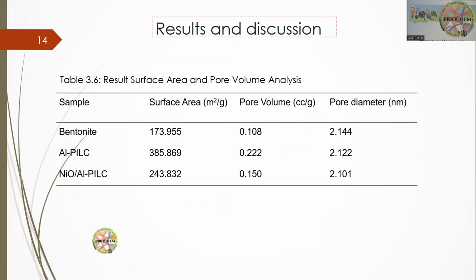So this is the BET result for the surface area, the pore volume and the pore diameter. You can see here, from 173.955, we are able to increase the surface area to 385.869. But as we impregnate nickel oxide onto the clay, the surface area decreases. But still, compared to the bentonite, it is still a significant increase.